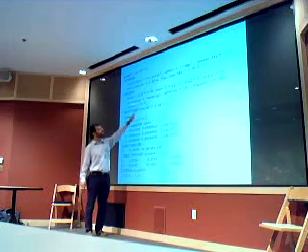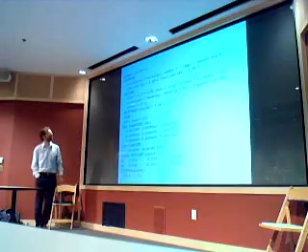So the input, let's say, for an arsenic variable cell relaxation at zero pressure is like that. You need to specify what type of calculation you want to do, and you say vc-relax. Then you don't need to specify anything of this because they are already set by environment variables in your case. Then you specify the threshold for convergence for the energy and for the forces.